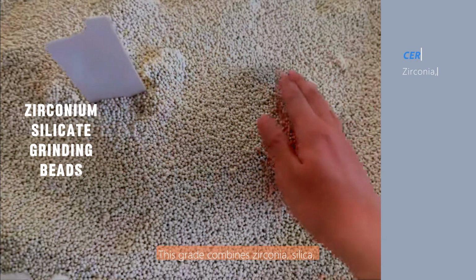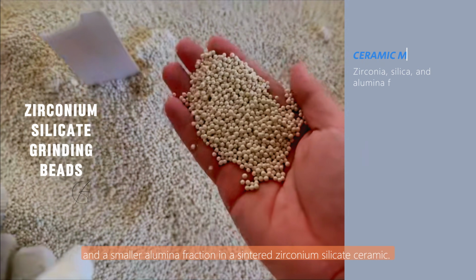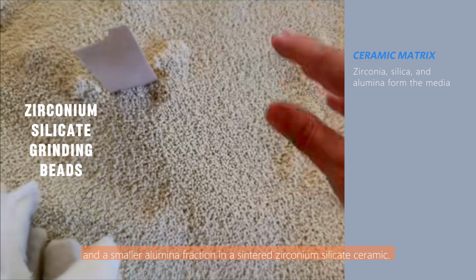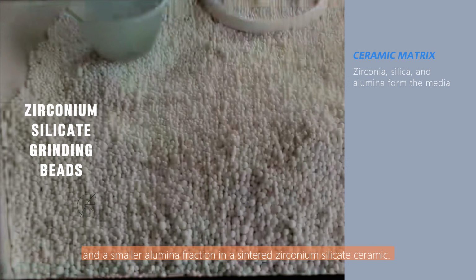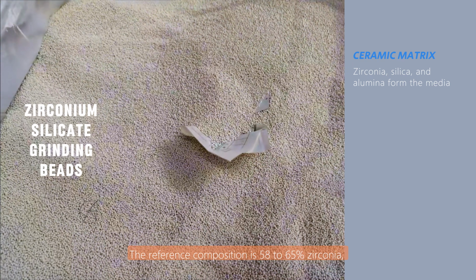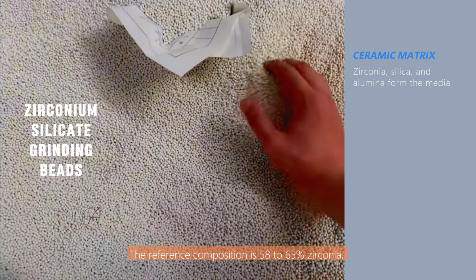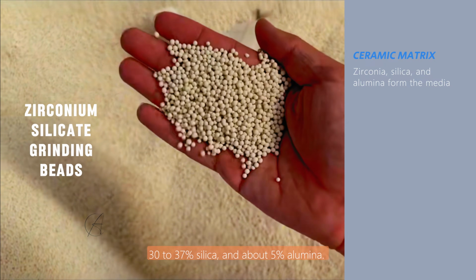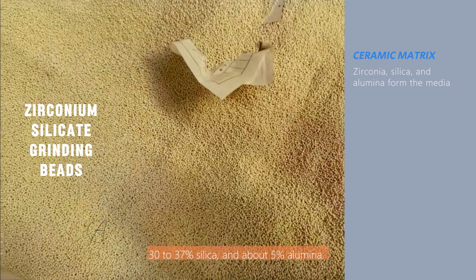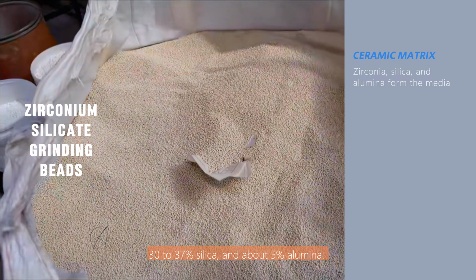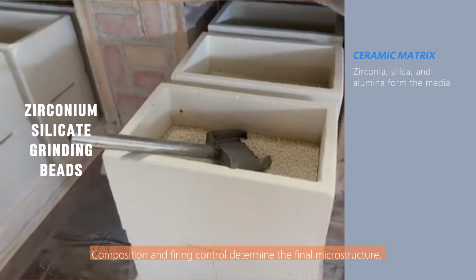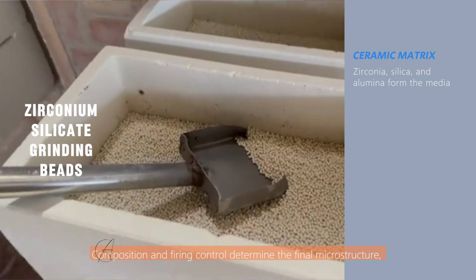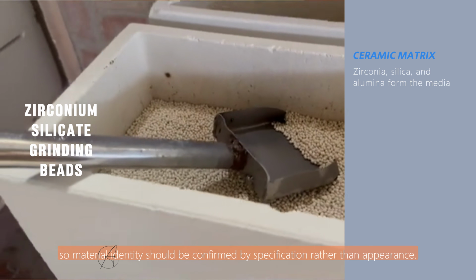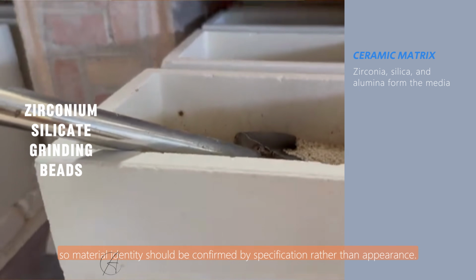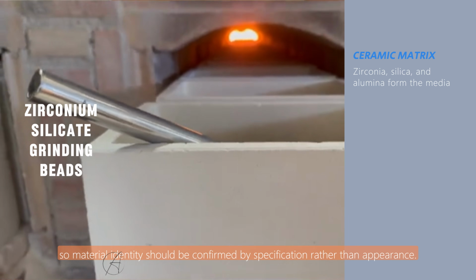This grade combines zirconia, silica, and a smaller alumina fraction in a sintered zirconium silicate ceramic. The reference composition is 58 to 65% zirconia, 30 to 37% silica, and about 5% alumina. Composition and firing control determine the final microstructure, so material identity should be confirmed by specification rather than appearance.